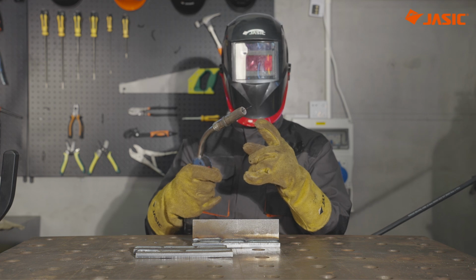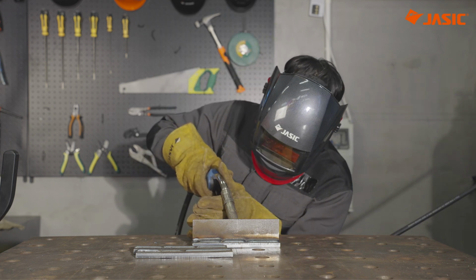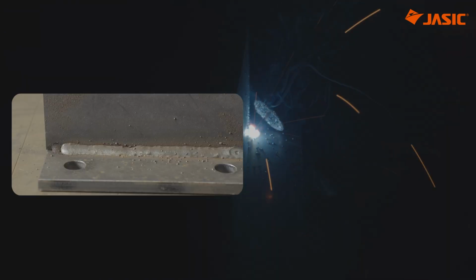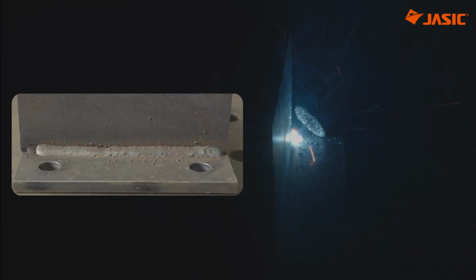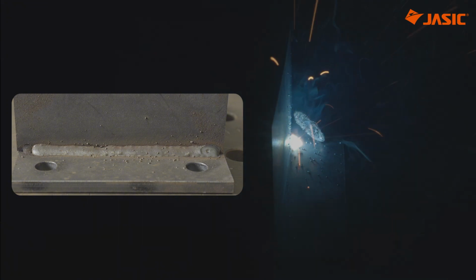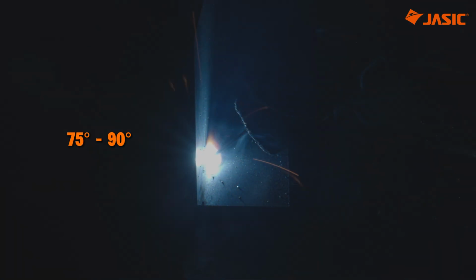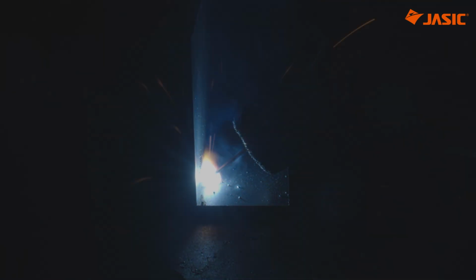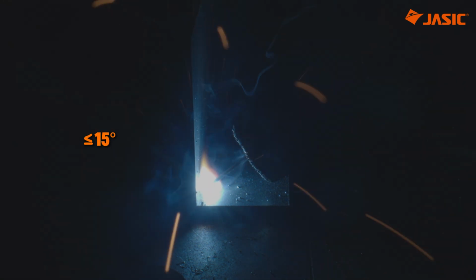Torch angle is another important factor. If the torch is tilted too much, such as around 45 degrees, the shielding gas is blown away from the weld pool. At the same time, the side force from the gas flow disturbs the molten pool, increasing spatter and making the weld bead less consistent. In practice, it is best to keep the work angle between 75 degrees and 90 degrees, while the push or drag angle should generally stay within 15 degrees.